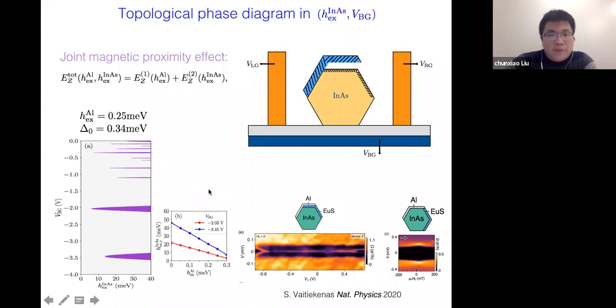And then we want to see how this minimally required exchange coupling evolves with the exchange coupling inside aluminum. In this particular case, these two values are at aluminum exchange coupling of about 0.25 meV. We see that when the exchange coupling in aluminum decreases, the minimally required exchange coupling will increase. Actually, if you compare this value at, say, 0.25 meV to 0, you find that the difference can be as large as 5 times. So the required exchange coupling is 5 times larger than in this particular case if there's no exchange coupling inside aluminum.